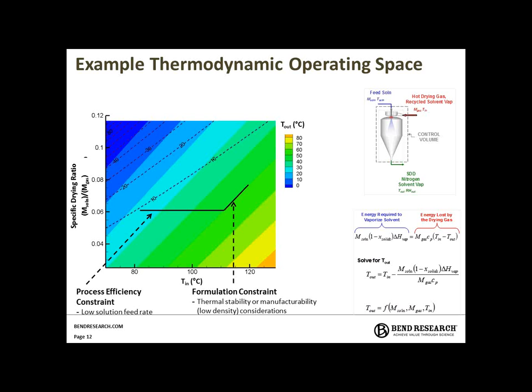So this could just be a thermal stability constraint of a given formulation where if the material is at that outlet temperature for too long of a period, you might start to see degradation. The other constraint shown here follows an inlet temperature contour, which could just be something like formulation browning at the hot spot of the spray dryer, although we try to minimize that, where the drying gas is actually coming into the spray dryer.